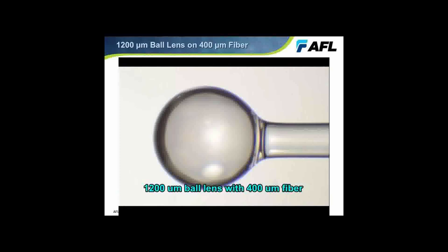We can see the microscope image of the completed ball lens. In some cases a normal ball lens shape is not desired — we call the normal shape type 1, but by changing motor parameters and control algorithms, we can achieve something like a hemispheric lens on the end of a fiber — type 3 — or something in between, a type 2 shape. We've also been asked to create a ball lens with a bent shaft on the fiber, achieved by a secondary process where we heated the shaft after generating the ball lens and used another fiber to put downward pressure during heating to bend the fiber.